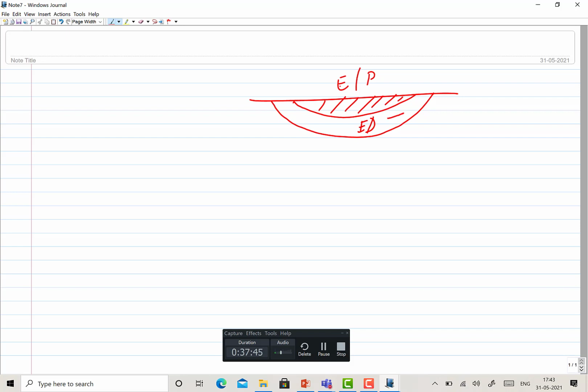So this elastically deformed zone is known to cause the following. The surface layer has been removed, and below that you had the elastically deformed zone, which will try to shrink because it has been elongated in the process of grinding. This effort to shrink will lead to the development of residual compressive stresses, meaning the surface will tend to shrink. So the presence of the elastically deformed layer is contributing towards the development of residual compressive stresses. These compressive stresses are there even when there are no external tensile stresses, no external load. So this is one aspect.